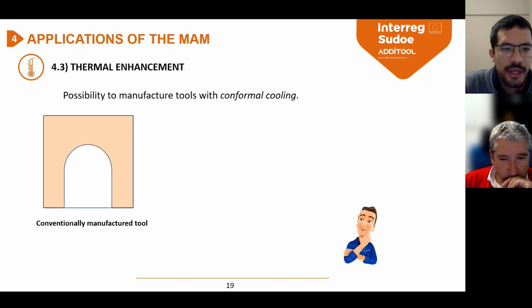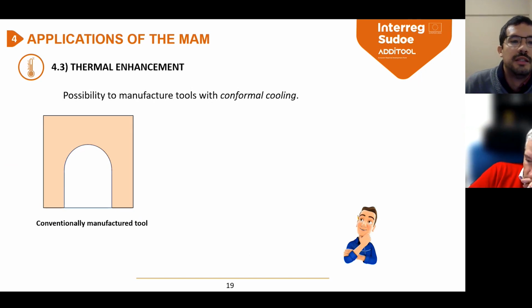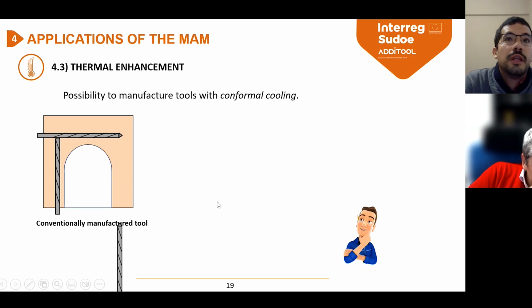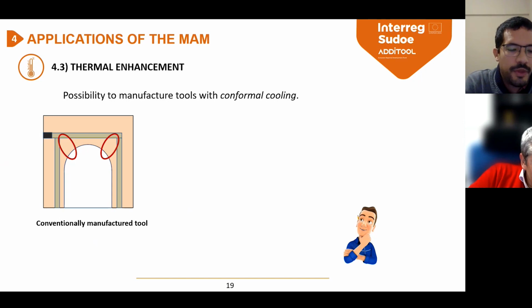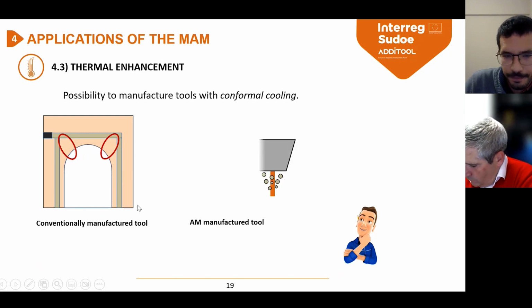The third example that we are going to analyze is the thermal enhancement. In this case, if we want to manufacture hot stamping tool steel, we also need to manufacture, via drilling, the cooling channels, which are always straight-shaped. And this implies that the distance between the active face, which is the inner line here, and the coolant channel is not constant, and we will have some kind of hot spots where the heat is not extracted, as well as areas where the drilling hole is close to the surface.